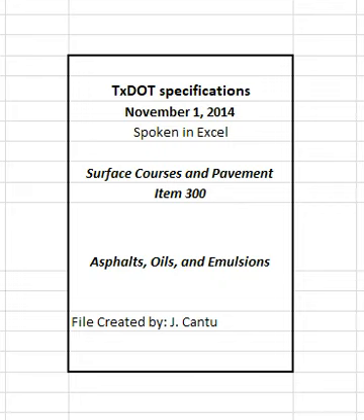4. For quality control of unmodified asphalt binder production, measurement of the viscosity of the original asphalt binder may be substituted for dynamic shear measurements of G*/sin δ, at test temperatures where the asphalt is a Newtonian fluid. Any suitable standard means of viscosity measurement may be used, including capillary, T201 or T202, or rotational viscometry, T316. 5. Silicone beam molds, as described in AASHTO T313, are acceptable for use.